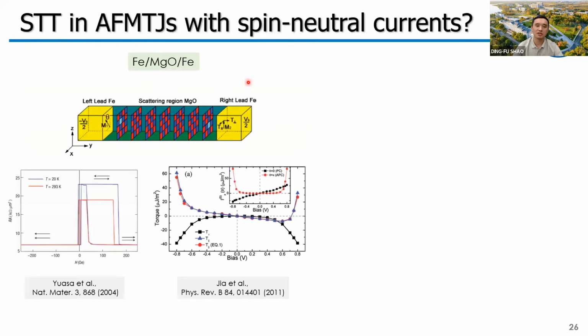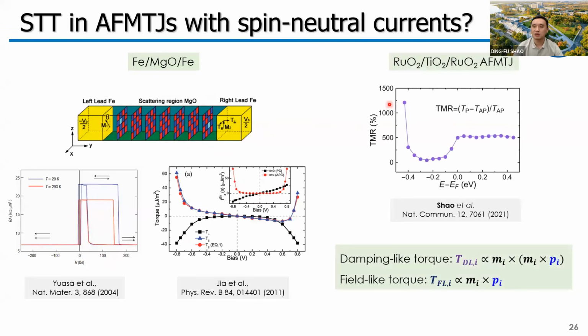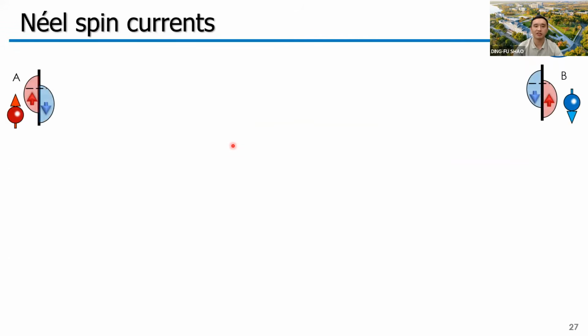But consider the conventional magnetic tunnel junction: if we have a giant TMR, we usually will also have a sizable STT. And since we have just demonstrated that in an antiferromagnetic tunnel junction we can also have a giant TMR, then I believe the STT can be realized as well. But the matching conduction channel mechanism cannot give me the answer to this question. So in order to solve this puzzle, I decided to check the local transport properties of antiferromagnets.